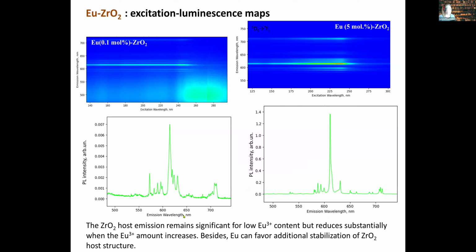And just one slide to show you the variation of europium emission when it has a very small amount of europium, about 0.1 mole %, and when we have about 5 molar %. I took two maps, a bit shifted in the wavelengths, but here you can see that in this left map, we see the good emission from the host and red emission from the rare earths. But when we dope with a high amount of europium, the emission from the host disappears.